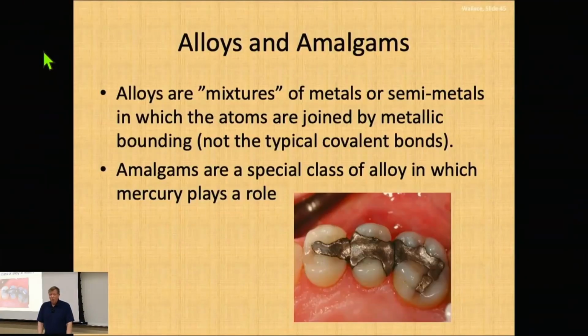I want to then go quickly to the alloys. Alloys are mixtures, so they have structure, but they're mixtures. And so unlike all the minerals that we talked about up to this point except for the native, they actually have a metallic bond. So when we add silver to antimony, or silver sometimes to arsenic, but mainly antimony, we make a metallic bond. So we make dyscrasite. Or if we add it to mercury, we make a series of amalgams, of which Eugenite is the most common. And you can see the fillings that were there.